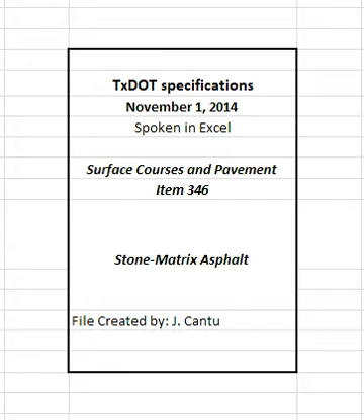4.9.3.3.4 Recovered asphalt dynamic shear rheometer, DSR. The engineer may take production samples or cores from suspect areas of the project to determine recovered asphalt properties. Asphalt binders with an aging ratio greater than 3.5 do not meet the requirements for recovered asphalt properties and may be deemed defective when tested and evaluated by the construction division.